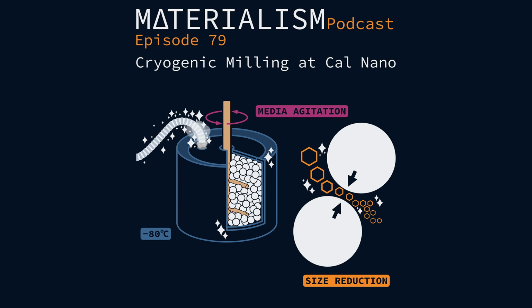Sure, some magic chemistry, but it's also the milling process, you're saying. The milling process, the cryomilling process specifically, reduced that grain structure to such a small nanograin that it prevented the crack propagation that would occur in a larger grain material. And combining that with the SPS to limit grain growth made it the highest compression strength material. It was with University of California, Riverside. Oh, yeah, UCR. What professor? Suveen.